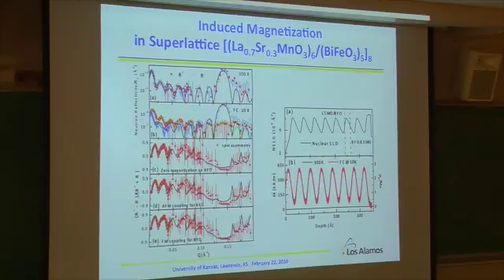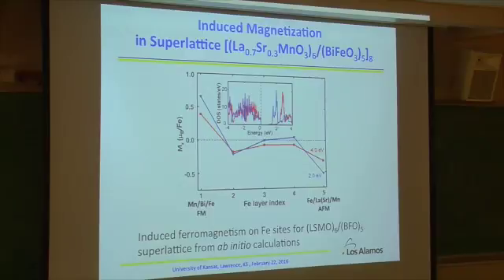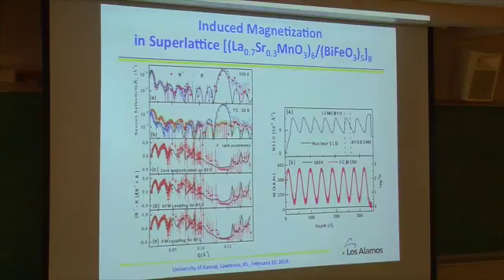Actually, we did this kind of simulation. We said, well, that's interesting, let's take a look. Another important thing I'd like to remind you is that here is really quantitative information. If you look at, for example, a SQUID measurement and check the magnetization, they agree very, very well, almost exactly with the SQUID measurement result. So it's really the first time we believe, quantitatively, for this material system, that yes, they do couple to each other.